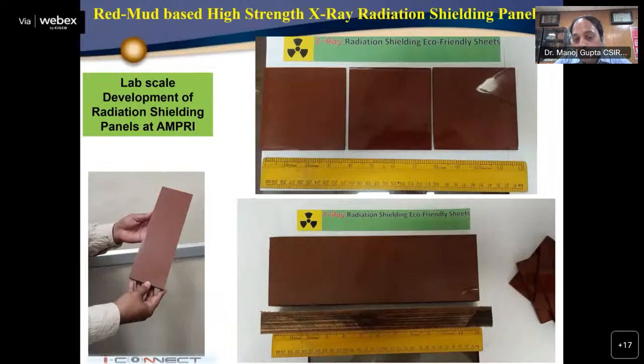So after a lot of optimizations and surface modification of the red mud through the compression molding machine and other processes, we have developed such kind of blocks. You can see this is the size of 10 centimeter by 10 centimeter, also 4 centimeter by 4 centimeter, with thicknesses of 1 mm, 2 mm, and 5 mm. We have developed this kind of product, which has very low water absorption and high mechanical strength.